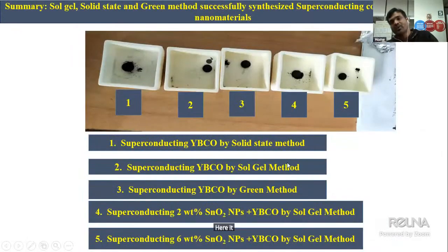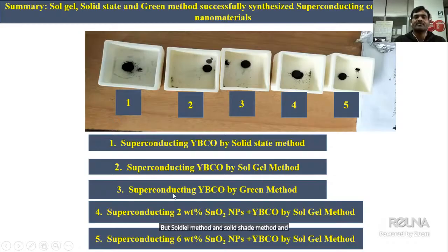Here we have successfully prepared the YBCO superconducting material by the sol gel method, the solid state method and the green method. The superconducting material from the green method is superior, as shown by the SEM analysis. Clearly we notice the particles are more dispersed in the green method, and we also prepared the sol gel method YBCO superconducting material with 2 weight% and 6 weight%, a lower amount and a higher amount of nanoparticle.